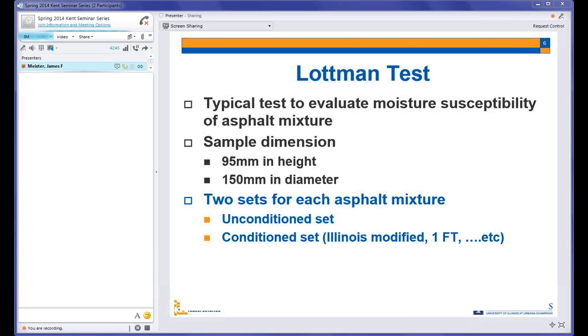One set we call the unconditioned set, which we don't condition, except we just put them for 2 hours in a 25 degrees water bath and then test it. And the other set is the conditioned set. Now it depends on which state you are working in. In Illinois, we have our Illinois conditioning procedure. You can also have 1 freezing thawing cycle, 2, 3, as much as you desire.